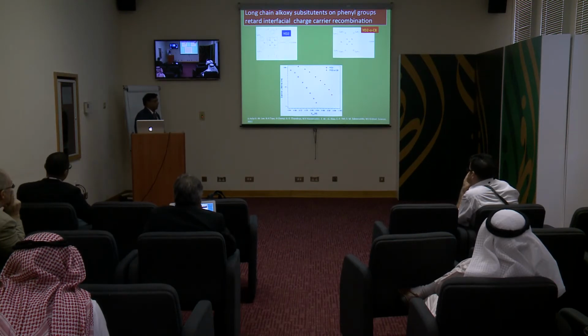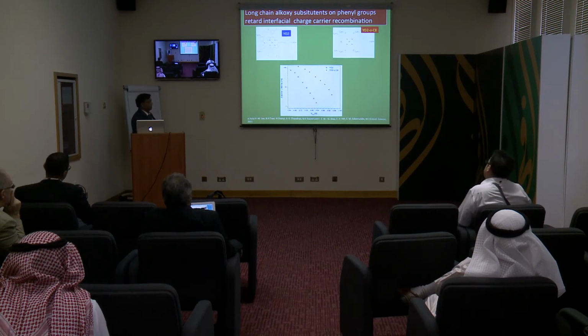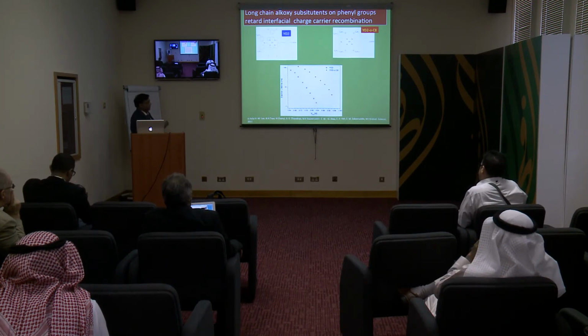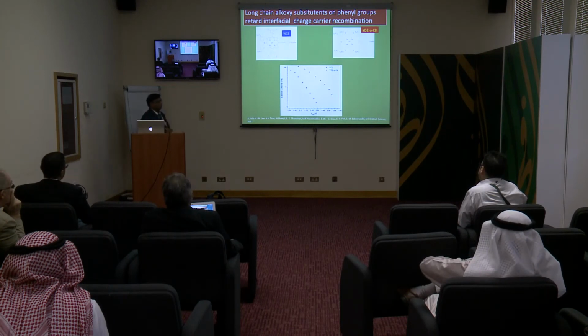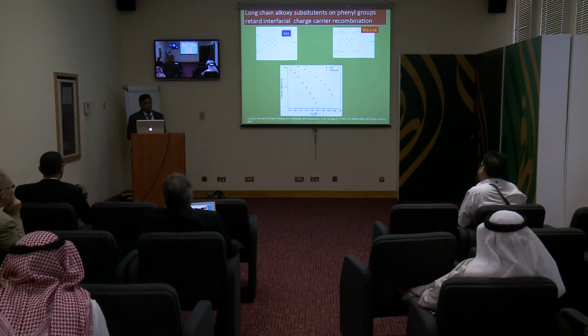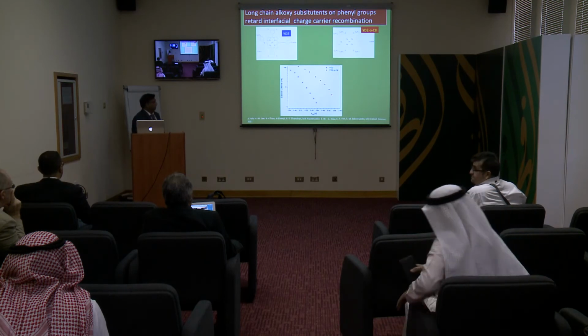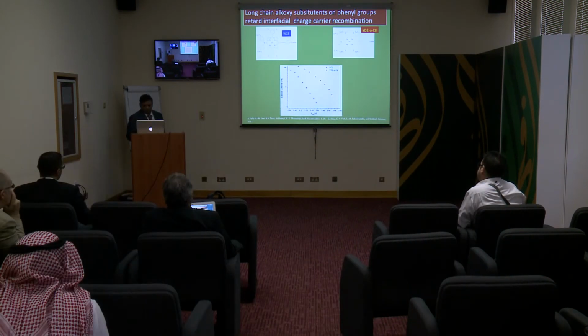If you measure this one, here the red one is the YD2OC8 with bulky group substitution. So you can see that we have a higher electron lifetime when compared to the other molecules, which is in agreement with the higher VOC we have seen.